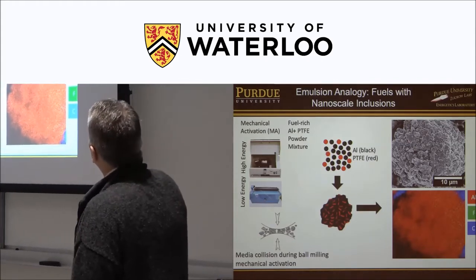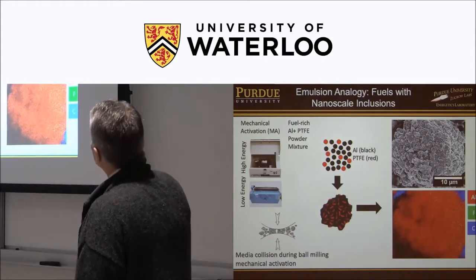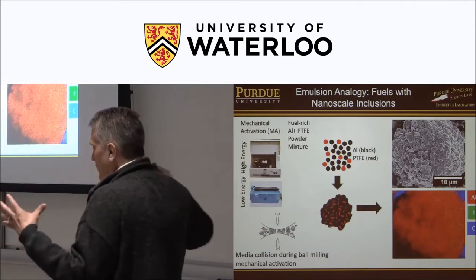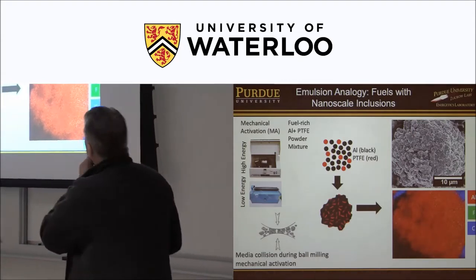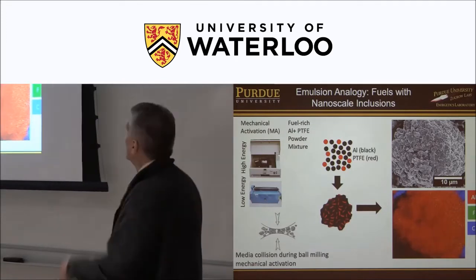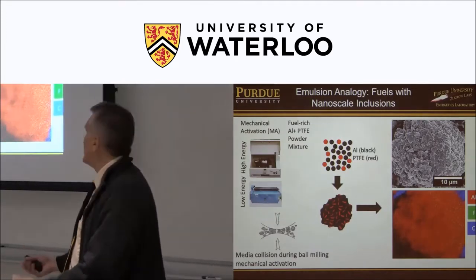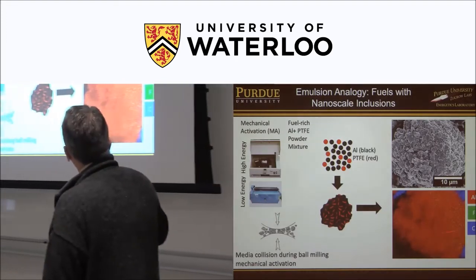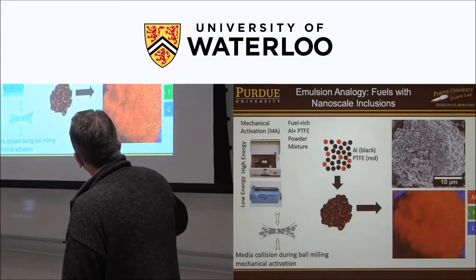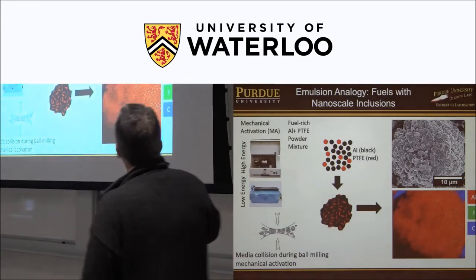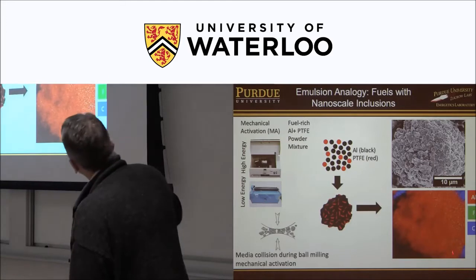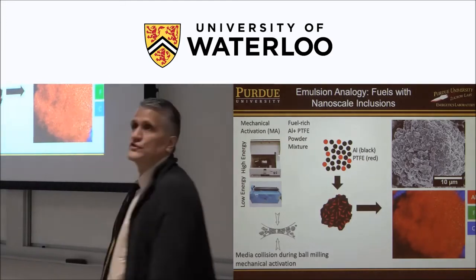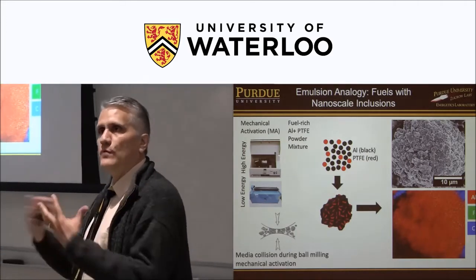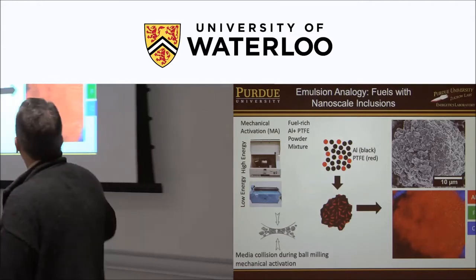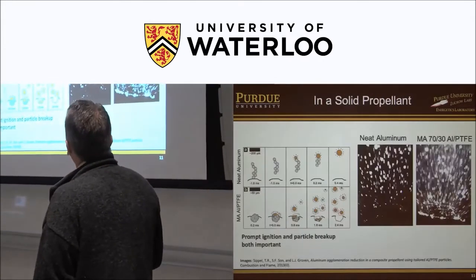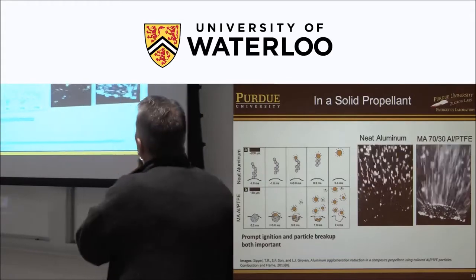This is an SEM image of that particle. This is 10 microns. So it's actually micron-sized, which has advantages in that it could be a drop-in replacement for just aluminum powders. This is looking at the EDS, the energy-dispersive spectroscopy. The green here doesn't show up too well, but it's very well dispersed throughout that particle. So we've got Teflon throughout that particle, and it is a nanoscale inclusion. So if we put that into propellants,